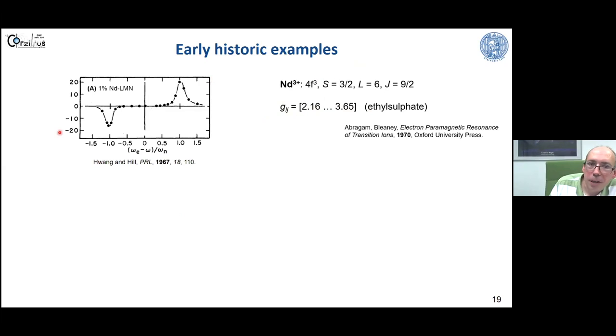The way this was done, in fact, was with a single crystal. So with a single crystal, you can orient the crystal in such a way that you ideally can hit practically a very narrow resonance because all the ions are oriented in the same way and you don't have any disorder in this crystal, or at least no significant disorder.